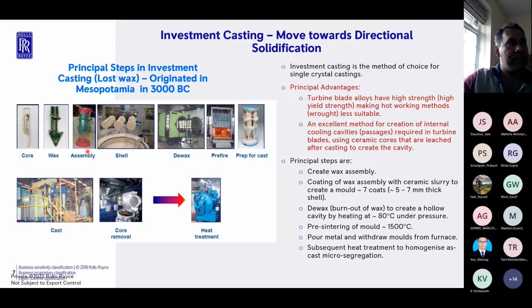You assemble a number of these wax patterns on a carousel. The point to make again is that you don't produce one component at a time because it's clearly not cost effective. You produce a number of components at a time, so therefore you align a number of such wax components on the base of a wax pattern. You then apply ceramic coating or shell around it. It's typically about 7 coats, and typically the thickness of the shell could be of the order of 5 to 7 millimeters.